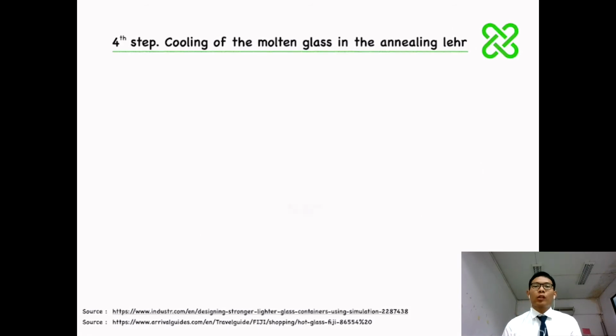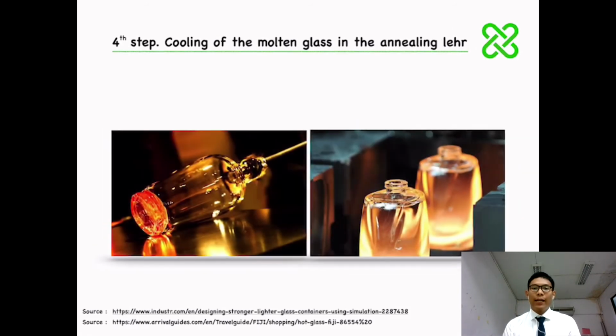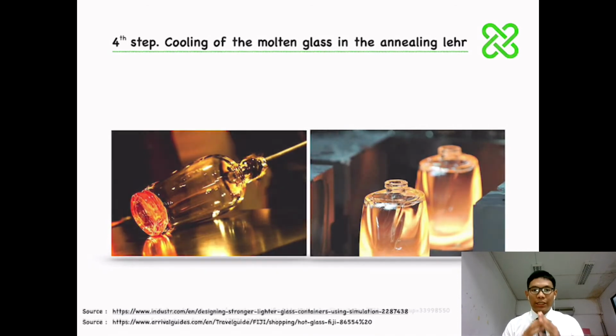Okay, now I will tell you the 2 remaining steps. Fourth step is cooling of the molten glass in the annealing lehr, after leaving the bath of molten tin. The glass, now at a temperature of 600 degrees Celsius, has cooled down sufficiently to pass through an annealing chamber called a lehr. The glass is now hard enough to pass over rollers and is annealed, which modifies the internal stress, enabling it to be cut and worked in a predictable way and ensuring flatness of the glass. As both surfaces are fine finished, they need no grinding or polishing.